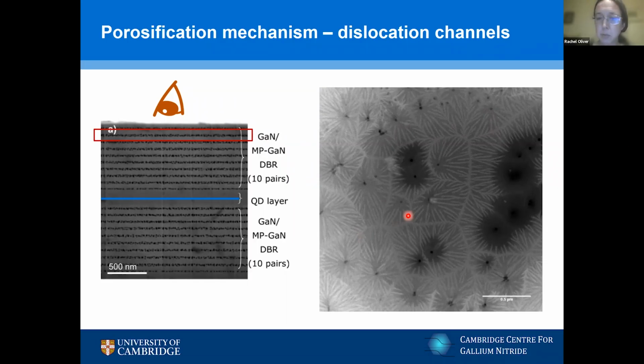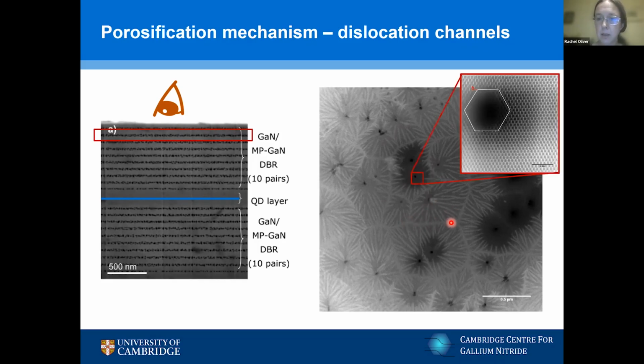And what we see in this porous layer are these little black holes. Emanating from those holes, the mid-gray is the pores, with the white being the walls between the pores. And we can see that the pores emanate out from these little dark holes, and where pores emanating out from different holes bump into one another, then we have a kind of wall between the two domains.